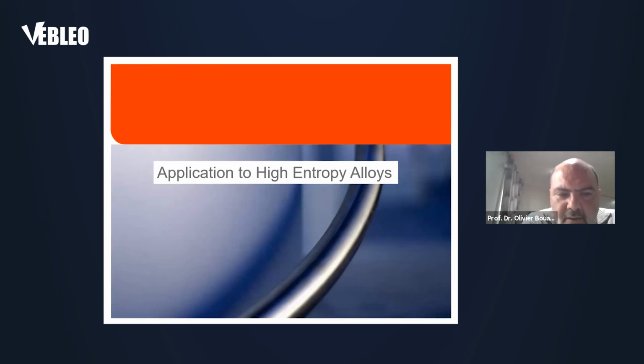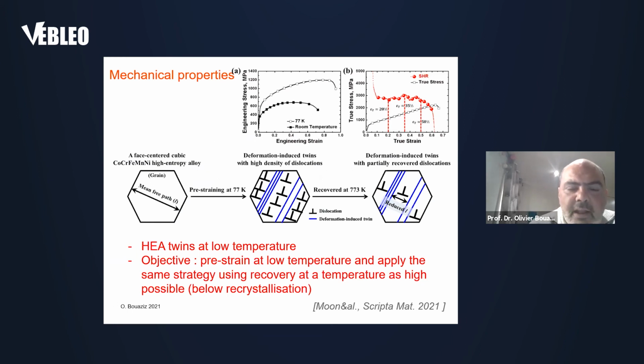So, a more recent application: we have applied this metallurgical route to high entropy alloys. So it is a Cantor alloy. In high entropy alloys, you can see the stress strain curve at room temperature and at liquid nitrogen temperature. The situation is a little bit different in this case because the twinning occurs at low temperature, not at room temperature. So what we have done, we have pre-strained the high entropy alloy at liquid nitrogen temperature, and after we have recovered at 773 Kelvin to reduce the dislocation density but keeping the twins.